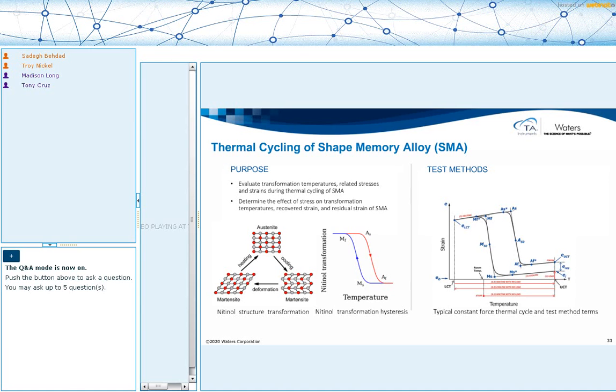You apply a load, and you can see that your sample experiences a strain because of that load. That's where you record your initial strain, or εi, and now I start to cool. As I start to cool, in the beginning, it behaves like any other material. So you see a linear decrease in length. Your sample is contracting as you're cooling it down until you reach the starting point of your martensitic transformation. You're cooling your sample, but your sample is expanding because of that phase transformation, right? And then after it is completed, you start to see a normal behavior again, a linear decrease in dimension until you reach your lower conditioning temperature.